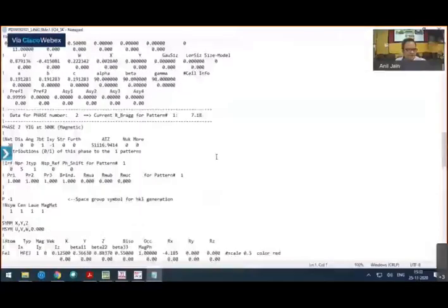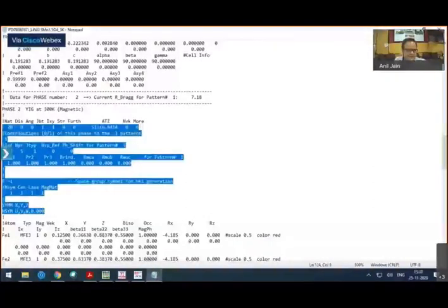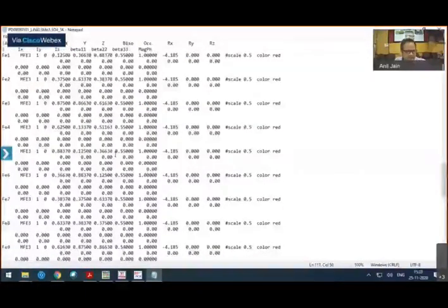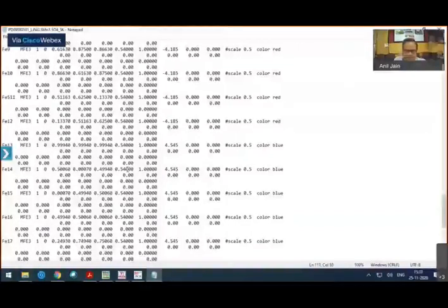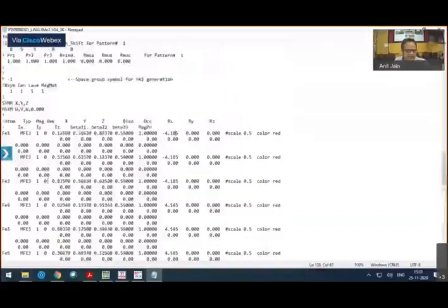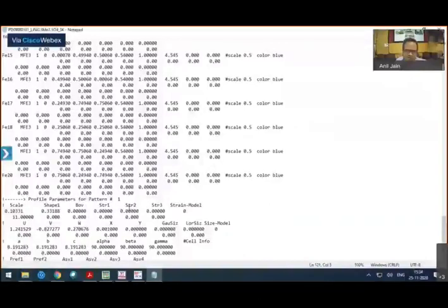Okay. Then what you do is, after you have finished this simulated annealing part, if you don't want to restrict yourself to the magnetic symmetries, then you can again add a phase, now here without more equal to 1, and whatever information you got from the simulated annealing, accordingly you can put your moment here in this PCR file. Now this is an additional phase, and here there is no restriction from the symmetry point of view, and then you can try to run this and see whether your crystal structure matches, whether your magnetic intensity matches or not.